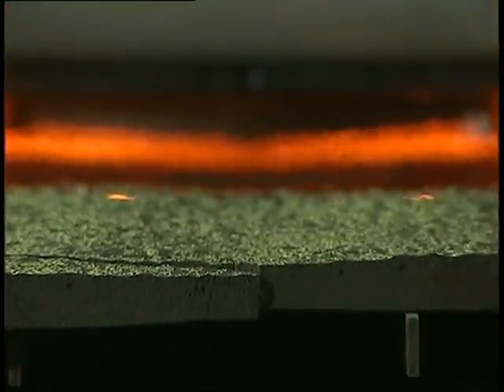A 10 millimetre thick mixture of glass and catalysing material is spread on the production belt. At a temperature of 900 degrees Celsius, the glass bubbles up to a froth some seven times its original volume. The plant is capable of producing as much as seven cubic metres of aerated glass per hour.